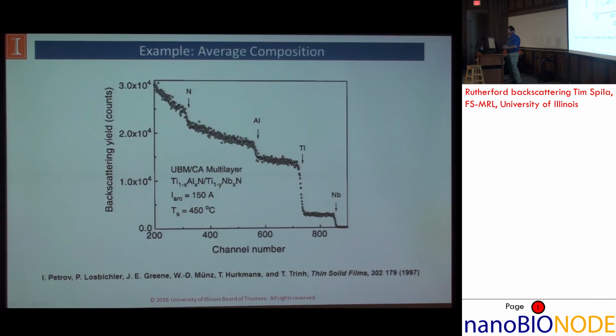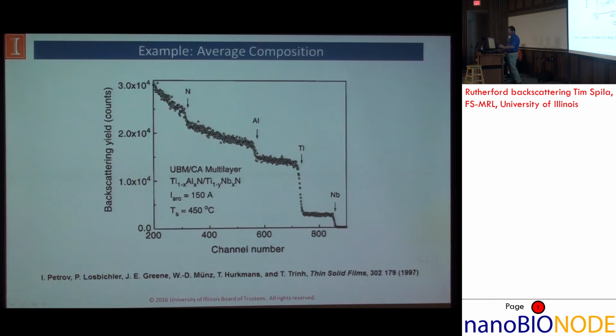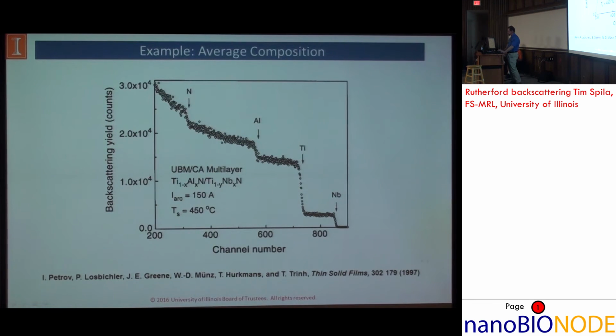A couple of quick examples here. This is a titanium aluminum nitride, titanium niobium nitride, multi-layer film with 2 nanometer periods. Not able to resolve that in RBS, but you can get average information. And so, of course, we have information from the niobium, from the titanium, the aluminum, and the nitrogen. Again, nitrogen being 50%, but it doesn't show very well because it's a much lower Z material.